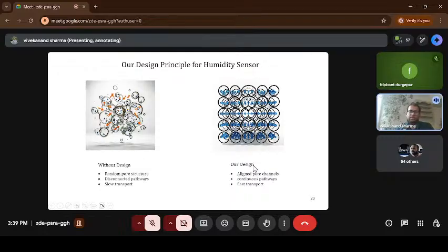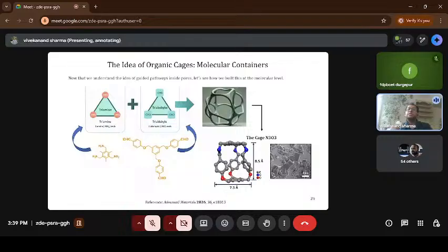So inspired by this type of foundational knowledge, we developed a material that was porous but was a discrete molecule. It was not a polymer, it was a single molecule which was porous from inside. It's like a cage structure. Here is a cartoon representation of the cage, and the actual molecule is like this one. You can see there is nothing, only blank space inside the material. We utilized very fundamental chemistry called Schiff base condensation. Using this molecule and this molecule, we synthesized this cage. The unique feature of this cage was the presence of an NH unit and an oxo group, O, from the top and bottom.